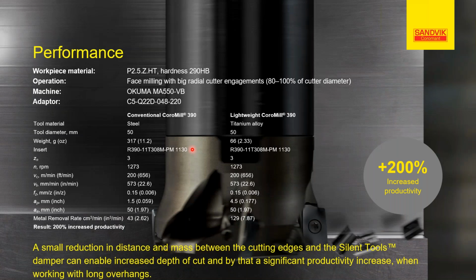Here you can see the performance. This is the same material, same hardness. You can see a conventional CoroMill 390 and a lightweight CoroMill 390. What happened? We can improve the depth from 1.5 to 4.5, so 3 times. So this solution allows us to reduce the vibration and to increase the productivity, plus 200%.